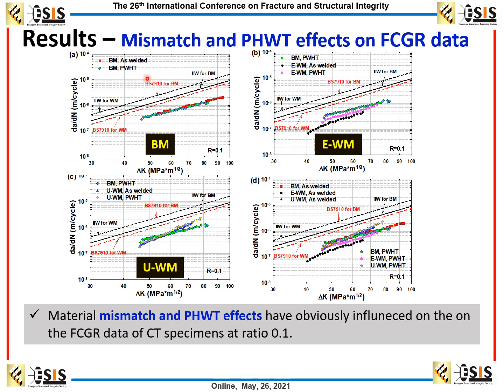The FCG data on the base metal compared with the BS 7910 and the IIW standard simplified Paris law reference lines. And it can be seen from the undermatched weldment figures that the difference between the as-welded and the PWHT state for the undermatched weldment seems to have no significant effect on the FCGR data at the stress ratio 0.1.